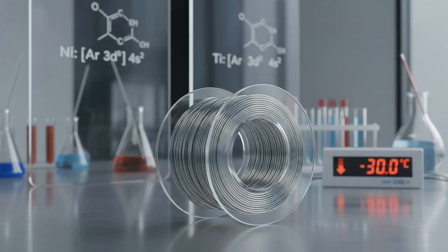Elastocaloric cooling requires superelasticity, the ability to undergo massive reversible strain, up to 10%, without permanent deformation. The gold standard for this is nickel titanium, also known as Nitinol. Nitinol alloys can achieve an adiabatic temperature change of up to 30 degrees Celsius in a single cycle. This is massive. It creates a temperature lift sufficient for refrigeration and air conditioning.